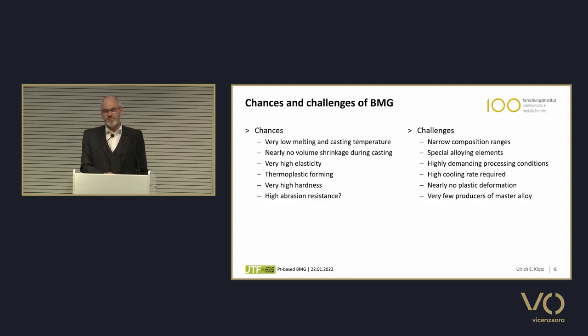So we see some chances and challenges of the bulk metallic glasses. They have very special properties, the very high elasticity. Thermoplastic forming was mentioned by Chris Corti as well. I will not go into depth in this. It's a special process. But on the other hand, there are some challenges, the very, very narrow composition ranges, the risk of embrittling if they're crystallizing, and of course the high cooling rate to reach the amorphous structure. And of course, this material is highly experimental. There are only very few companies that are nowadays producing such material.